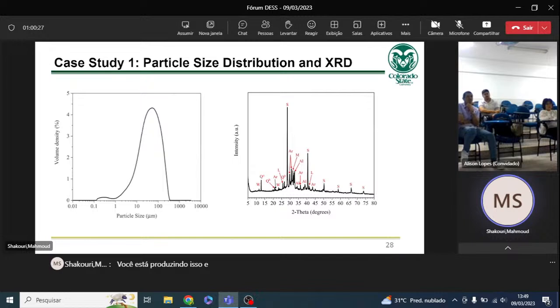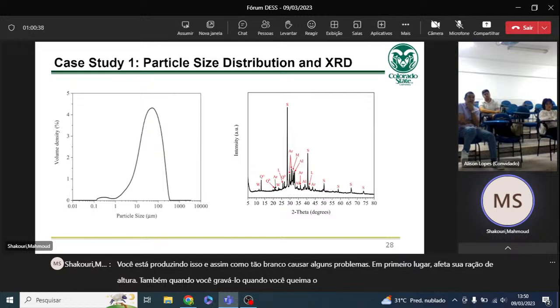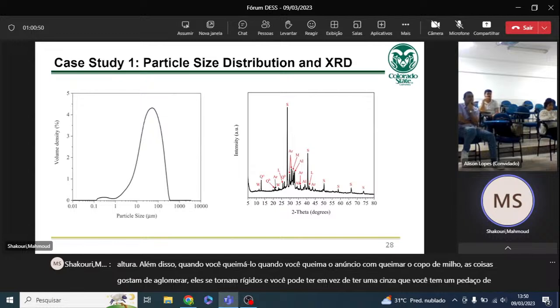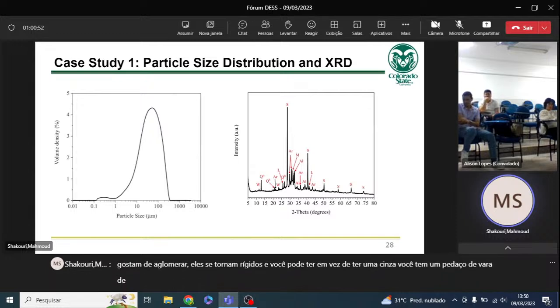So sylvite causes a couple of issues. First of all, it affects your hydration. Also, when you burn the corn cob, things like to agglomerate. They become stiff, and instead of having an ash, you have a chunk of ash stuck together. So that's the problem that we saw, and that's because of the sylvite.